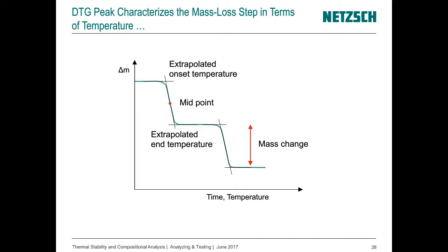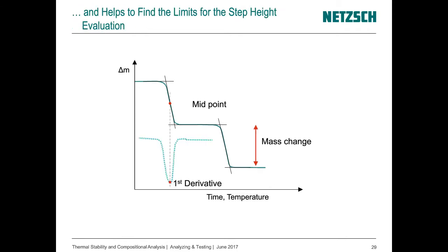The midpoint or the inflection point is identical to the peak temperature of the first derivative, and this is a temperature what we have seen already several times, and this is very often used as a characteristic value for characterizing the thermogravimetric effect. But the derivative is also used very often additionally for finding the right limits for the step height evaluation, because we have to define where to start and where to end the step height calculation.